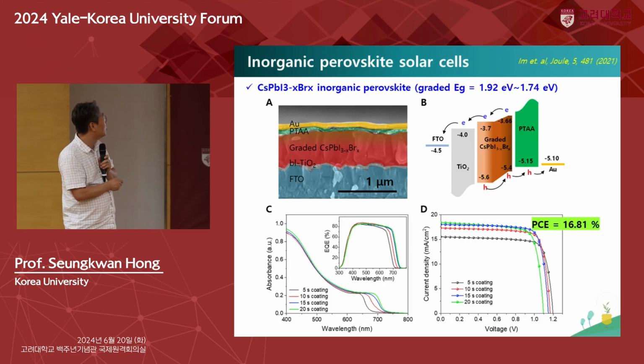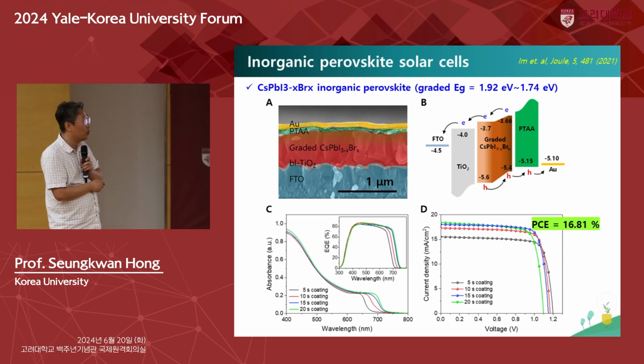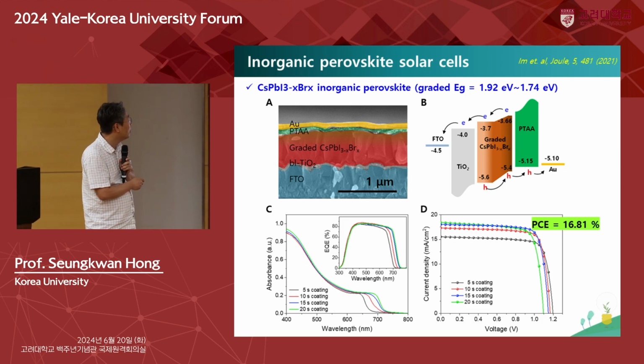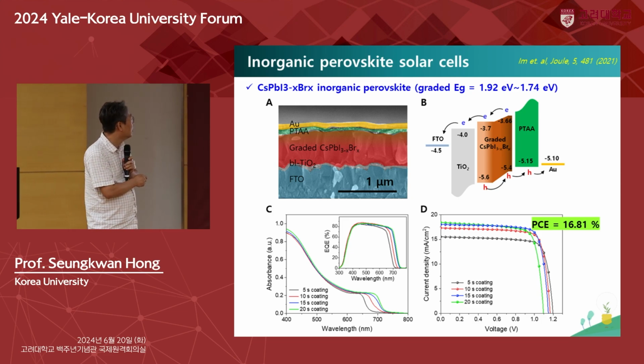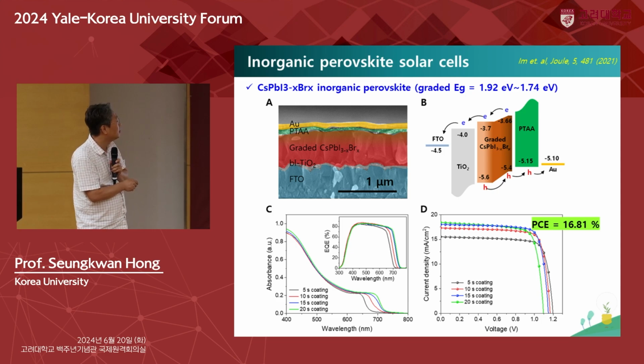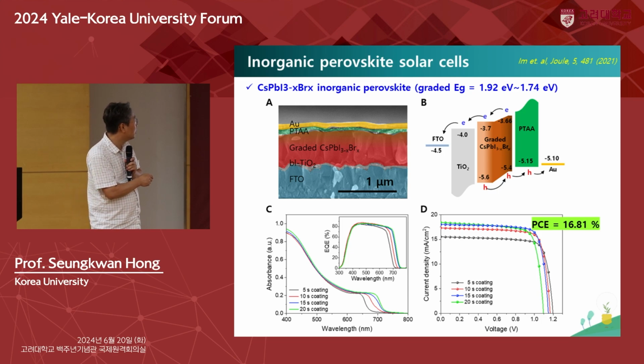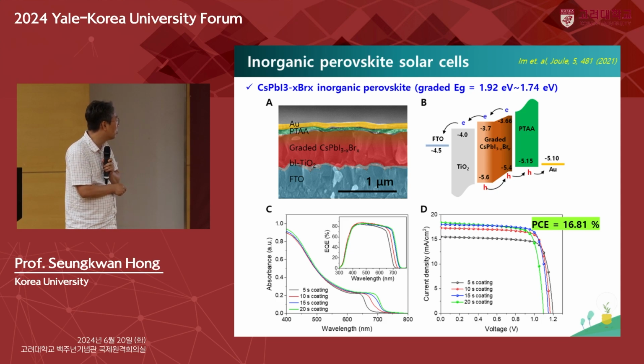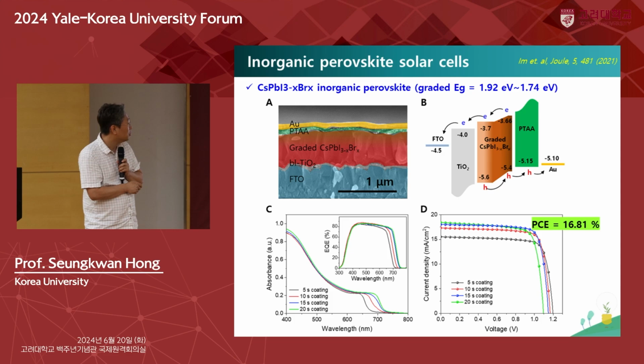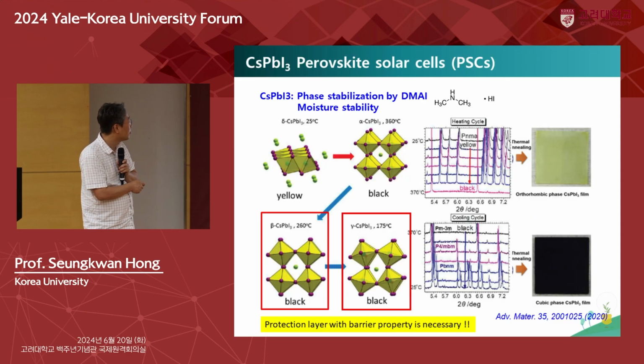So we started to fabricate the all-inorganic perovskite solar cell. Basically, we started to use the CsPbI2Br material. Then to extend the absorptivity in the long wavelength, we sprayed and made a graded structure. Then we can extend the absorption band edge to about 730 nanometers. At that time we could get about 17% efficiency.